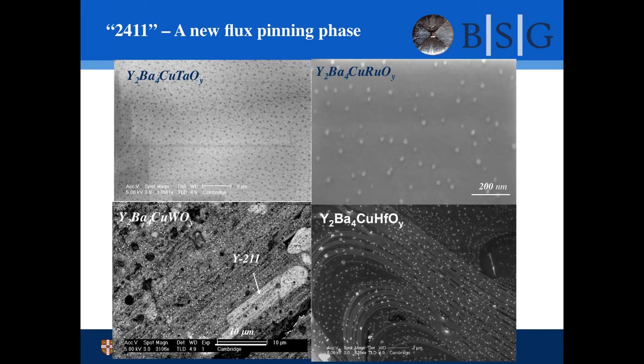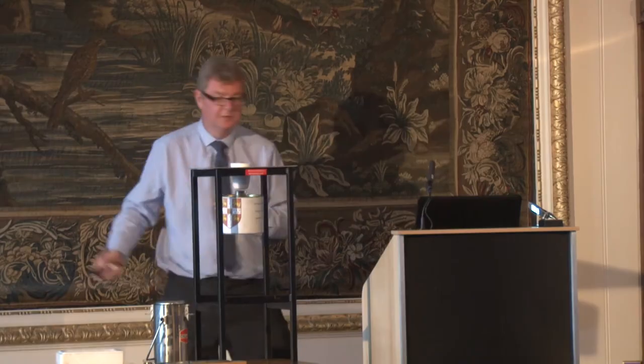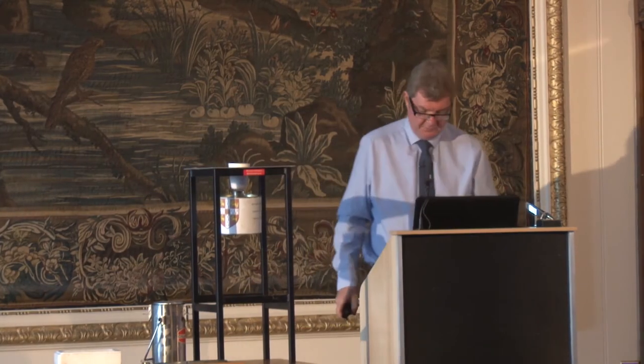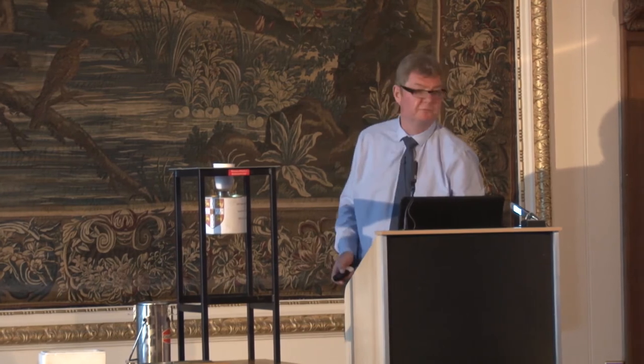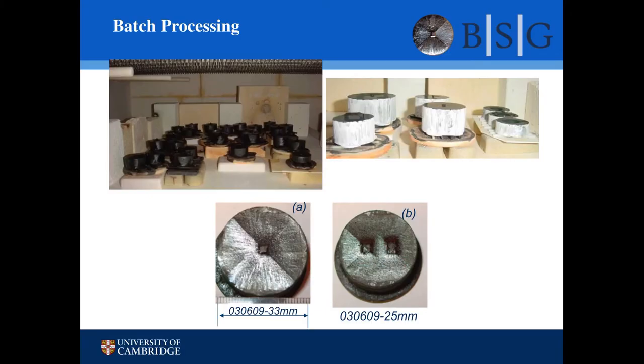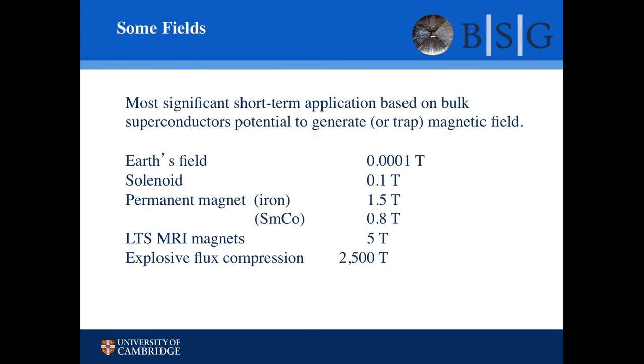And if you look at the bottom left picture, this is a big old 211 particle. And you can see these tiny white dots in between. And they're much closer to the dimensions of the flux lines and much more efficient at pinning magnetic flux than 211. So you can use 211 to grow the material, and you use this 2411 phase to pin flux. We can also batch process, so if you want a large number of these samples at a medium scale, we can do that as well.